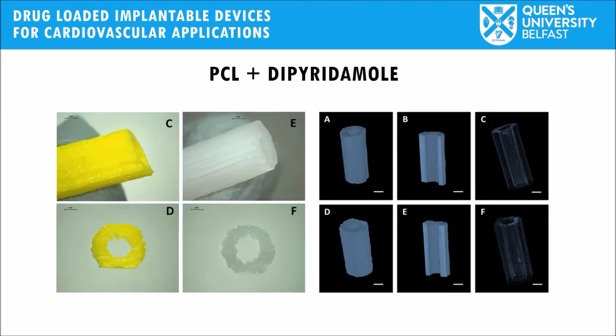On the other hand, we worked with dipyridamole. Dipyridamole, in this case, has color, it is yellow, it's a fluorescent molecule, and we achieved higher drug loadings. The drug loading went even up to 20%, which is the maximum concentration that was tested, 20% dipyridamole inside the implant. It was tested using computed micro CT. You can see that the drug was well dispersed in the material, as you can see in the CT images, so there were no accumulations of the drug or drug particles in any part of the vascular graft.